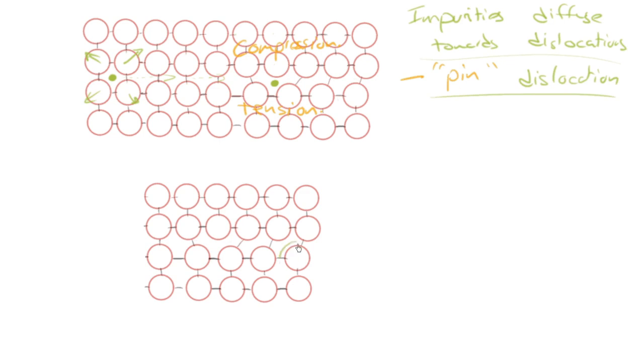And that increases the strength, because it makes it harder for that dislocation to move away from the impurity atom. Similarly, if we consider a dislocation coming across any of those other impurities that I discussed, like a substitutional impurity, the strain field surrounding the dislocation interacts with the strain field surrounding the impurity. And the general statement we can make, which is accurate, is impurities tend to inhibit dislocation movement. And so it's for this reason that impurities strengthen materials. So pure metal, like pure gold, for example, is really quite soft. And you add a little bit of silver, a little bit of copper to it, and the strength significantly increases. Pure iron, another example, not very industrially relevant, it's not very useful as an engineered material, but you add half a weight percent carbon, a tiny little bit of carbon that goes into interstitial sites, and inhibits dislocation movement, the strength goes way up, and now it's a hugely important engineering material to us. Alright, so imperfections are hugely important, and that was our look at point defects. Thanks.